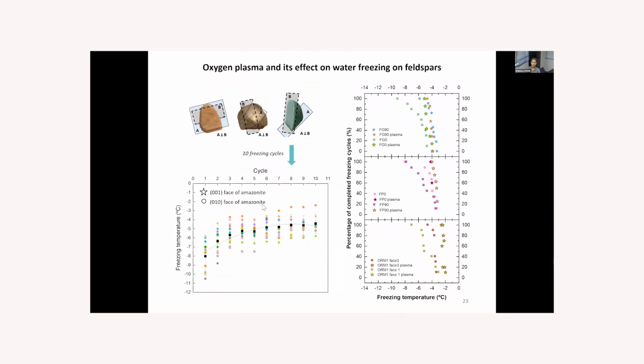Here, for example, you have the examples of plotting the freezing temperatures of different cycles of 10 of the cuts. 5 of them are on the 001 face and 5 others on the 010 face. The trend is that with consecutive cycles, the freezing temperature gets higher, gets to lower supercoolings. So the performance gets better.